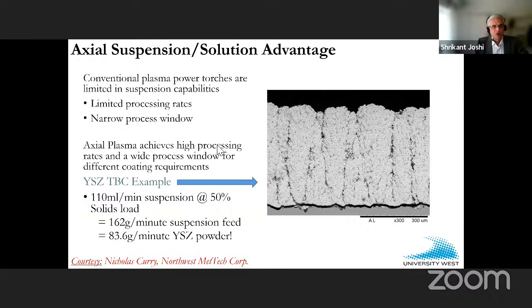We were talking a little bit about throughputs, right? Now this is a TBC example, of course. Now you're beginning to reach almost 50% solid load YSZ coatings using the suspension route, and these put you in a regime which is almost same as what you would typically get using a powder. As I will try and show you later if I have time. The same is true for chrome oxide, for example.